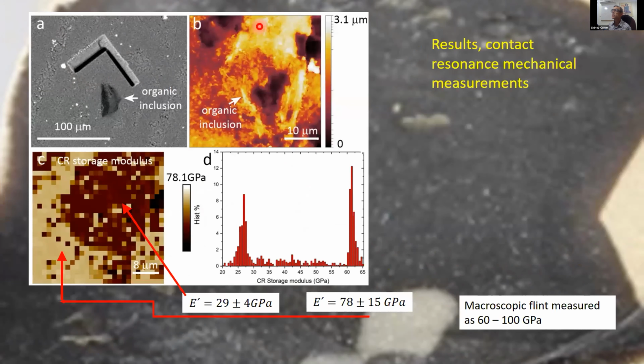So this slide shows a result of such a scanning probe measurement. This topographical view here shows the organic microinclusion. I want to point out that when we expose this to water or moisture, it swells, it noticeably swells. And furthermore, the elastic modulus drops very significantly.